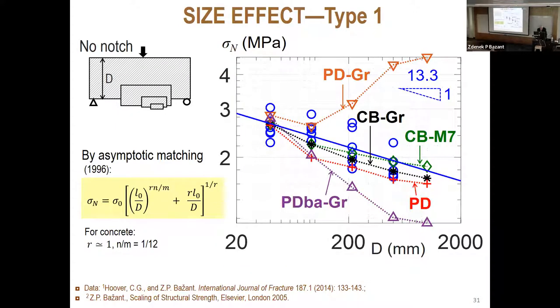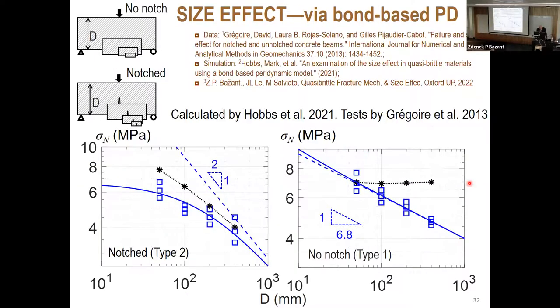And again, CBM7 and Grassel fit as well as the data scatter permits. And the other models are in gross disagreement. Phase field model, and actually the stopping of the effect prematurely is impossible. The same data again plotted, but other models shown here. So this is Peridynamics, Grassel, bond associated goes completely wrong. Peridynamics, this curvature is not right. Actually, you cannot get beyond this point. So, okay, so these are unsatisfactory or wrong actually.